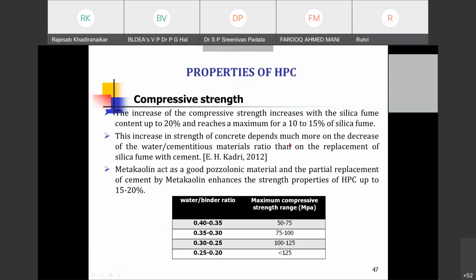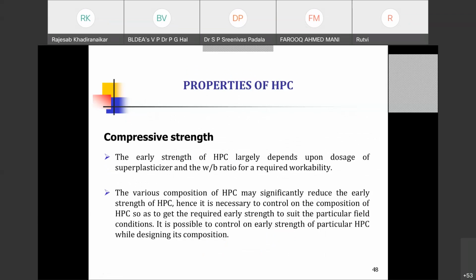The increase in strength of concrete depends much more on the decrease in the water cement or water binder ratio. Also the replacement of mineral admixtures. Metakaolin is a good pozzolanic material with a partial replacement of 15 to 20%. And in this range, with a water binder ratio of 0.4 to 0.35, they are able to get 50 to 75 MPa strength, and 0.35 to 0.3, it was 75 to 100. Then 100 to 125 for 0.3 to 0.25, and for the range of 0.25 to 0.2, it's around 125 MPa.